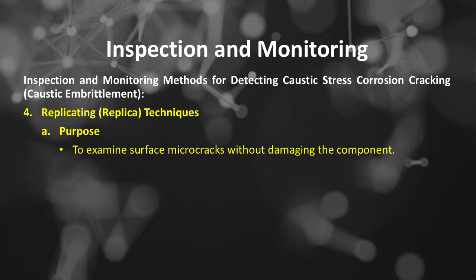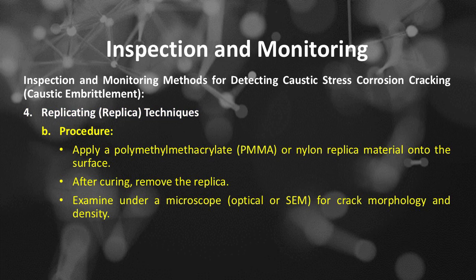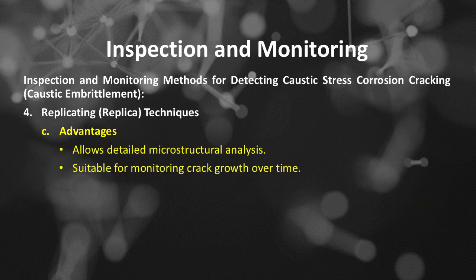Number 4 is replicating or replica techniques. It is purposed to examine surface micro cracks without damaging the component. Here's the procedure of replica techniques. Apply a polymethyl methacrylate or PMMA or nylon replica material onto the surface. After curing, remove the replica. Examine under a microscope, optical or SEM, for crack morphology and density. The advantages of replica techniques: it allows detailed microstructural analysis, suitable for monitoring crack growth over time.